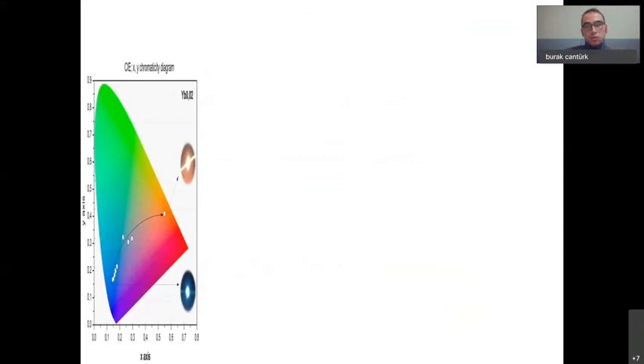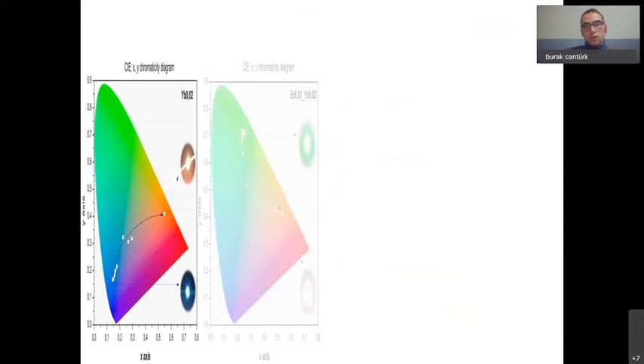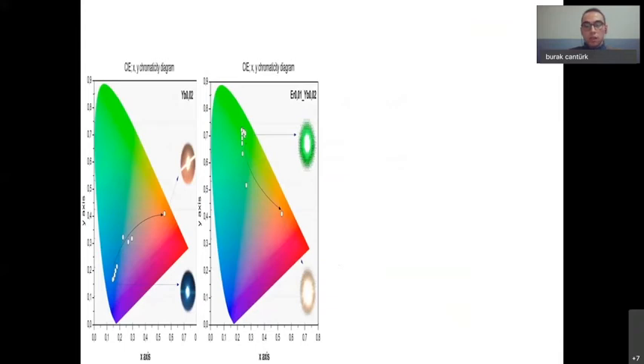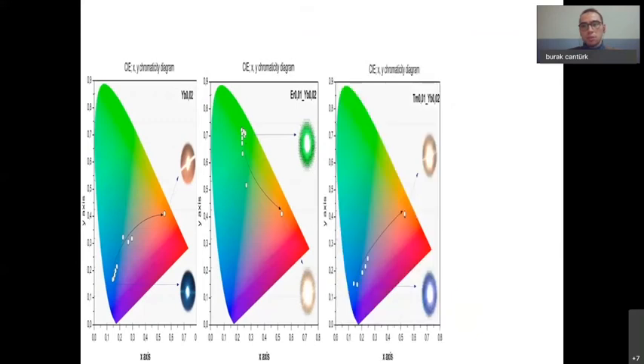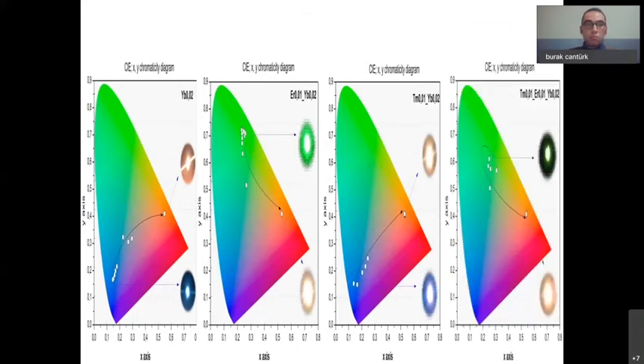So in addition to the previous slide, here we see the change in the color coordinates of the samples depending on the power. With the measurements made with the luminescence meter, we see the changes in the coordinates. At first, according to the doping ions, the samples emit blue or green color. But as we increase the laser power, the color coordinates change and the color also changes to yellowish white in every single sample. As a result, we saw the color changes. The reason behind this is thought to be the energy transfer mechanism between the ions.